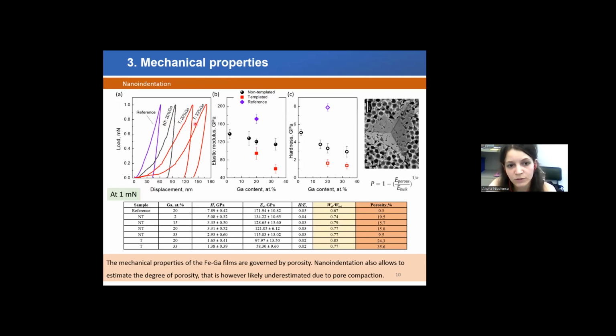From these load-displacement curves, applying the method of Oliver and Pharr, we could extract the values for elastic modulus and hardness, and they're plotted here. These are just the extracted numbers. We can observe that in both cases, the highest values are obtained for the reference sputtered and fully dense iron gallium film. For the same composition, for example 20 atomic percent, both elastic modulus and hardness decrease with the increase in porosity, and we also notice a decrease in both of these parameters with the increased gallium content. Another parameter that we could obtain from the load-displacement curves is the so-called plasticity index, shown here in this column.